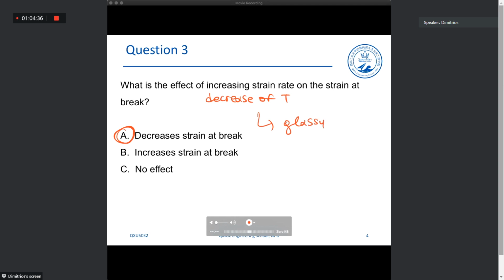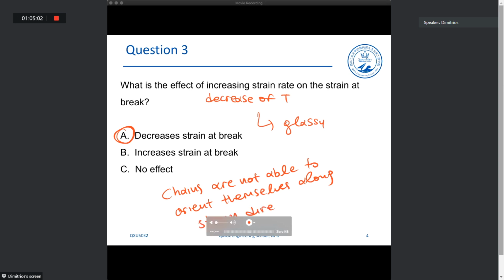Similar to glassy polymers, the chains are frozen, or we apply very fast strain, so chains are not able to orient themselves along the strain direction. Okay, there is not enough time for the chains to be able to orient along the strain, and because of entanglements and because of the high strain rate, the strain at break is significantly decreased. Strain at break, and as a result, of course, toughness.